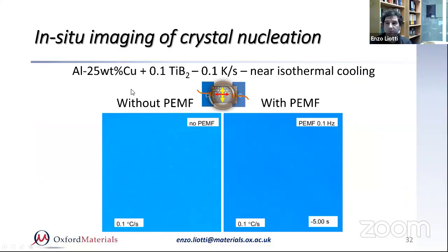Now, this other example is the effect of stirring. In this particular case, we took an aluminium 25wt% copper alloy, grain refined with TiB2, but cooled very slowly at 0.1 degree a second. Again, still in near isothermal conditions. What I'm showing here is the example without a PEMF, so without stirring, and with some stirring. The stirring here was done at 0.1 hertz. This is actually the video sped up for convenience, so it's going very fast.